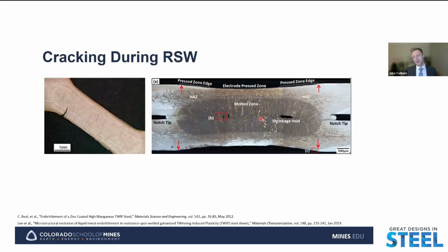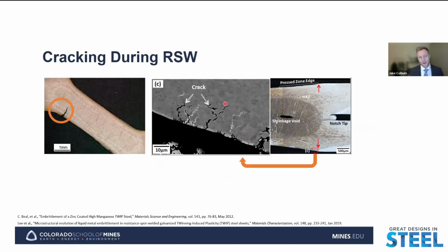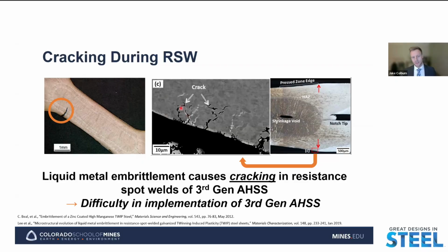However, when these third generation advanced high strength steels are galvanized with a zinc coating and then joined via resistance spot welding for the production process, we see that cracks can form along the weld shoulder and weld periphery, most notably for these steels. This cracking can lead to both the mechanical and aesthetic degradation of the welds, which makes it difficult for the automotive industry to implement these steels in automotive bodies.